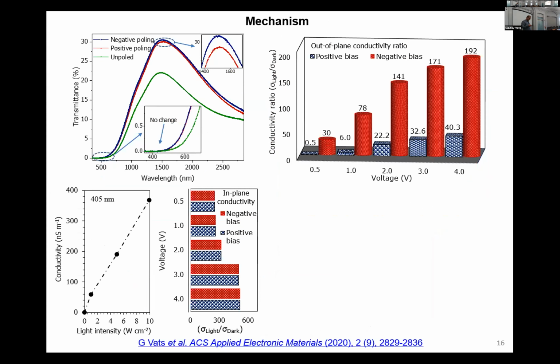Let's look at the mechanism of this. So I acquired this transmittance data, and here we are playing with this 405 nanometers wavelength, which is somewhere here. See the zoomed version here, and you see there is almost no change between the poled and unpoled sample. That means this 405 is fully absorbed by the sample. When the light is absorbed, there is a change in the conductivity, which we could measure. And this change in conductivity with applied voltages with the in-plane electrodes was going like this. And with out of plane, it's going like this. You can see the behavior is not linear, but it's slightly non-linear.